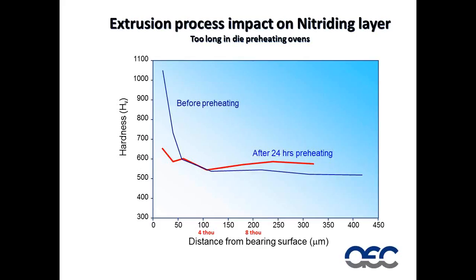And you can see we might as well have not bothered nitriding it. All the good stuff, all the stuff we have worked so hard to make right here is lost. The nitrogen simply diffuses at the preheating temperature out of the surface. So a key part of good nitriding is also good die preheating.